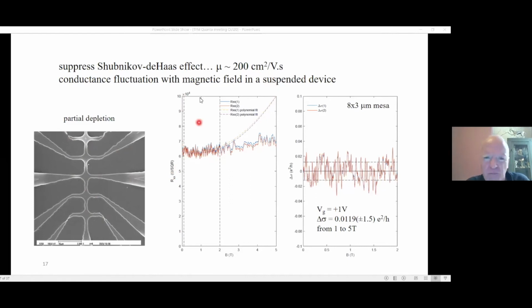We've completely suppressed any Shubnikov-de Haas effect. It's a completely different system to that. Mobility of a few 100 to 200 centimeters squared per volt second. So we've started with a reasonable mobility of about 20,000, and we've been able to reduce that so the device properly sees that disorder. But we're totally dominated here by conductance fluctuations, which are reproducible.